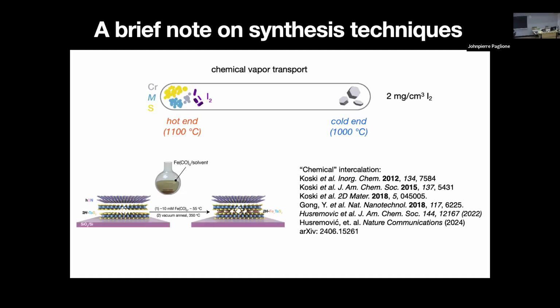And so I'm sure, talking about synthesis here in this school, maybe CVT has been one of the topics, so I don't want to go too much into that, but the general idea is you can have the elemental precursors on one side of a sealed ampule with some transport agent that volatilizes them, and then they crystallize on the other side. The energetics of the formation of that volatile product and the formation of the final material will determine whether you end up growing at the hotter end or the colder end. Whether the reaction is endothermic or exothermic is going to determine that. And this is actually a very common purification method for metals in industry.